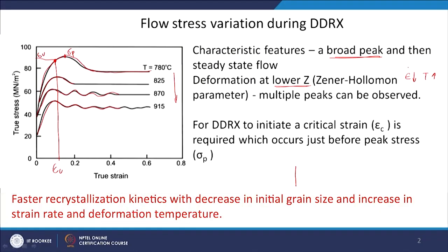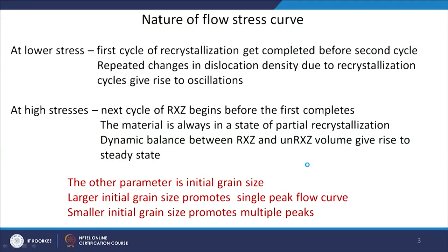Usually it also follows the S-shaped curve as in phase transformation. If I have 0 to complete recrystallization as a function of time, it will have some behavior like this S-shape curve. The kinetics — that means the time required from start to finish — will decrease with initial grain size, and at higher deformation temperature it will take lower time to complete the recrystallization process.